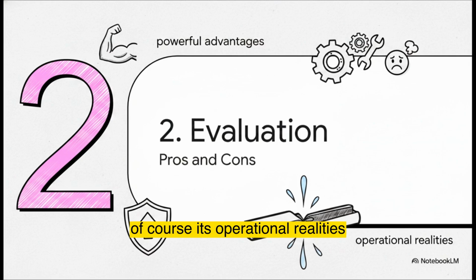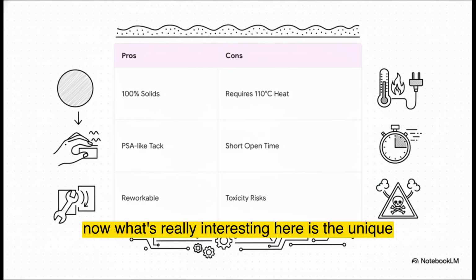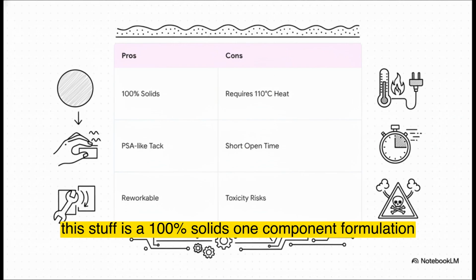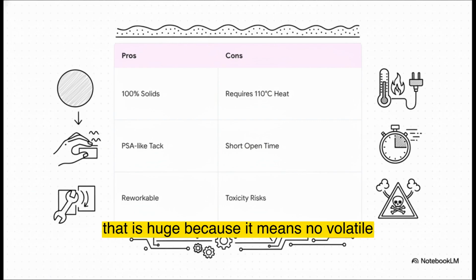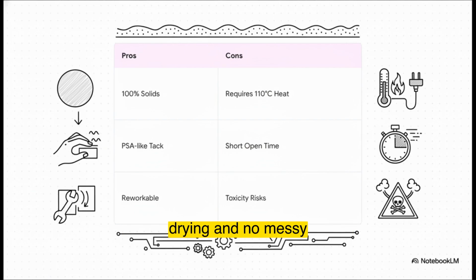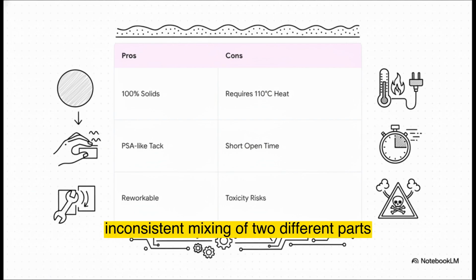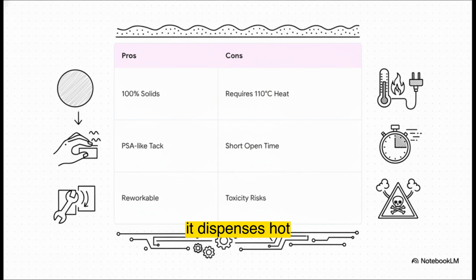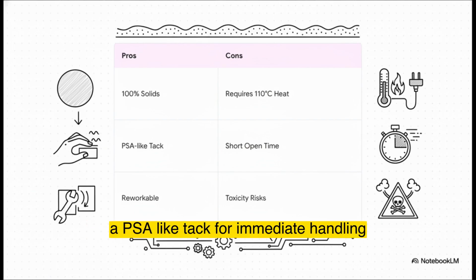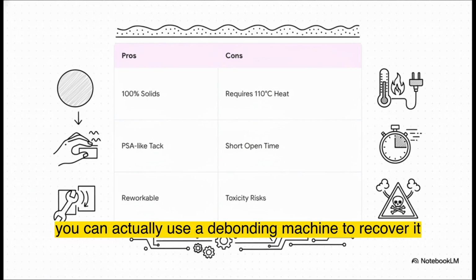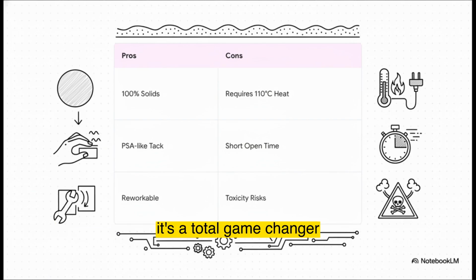Now, what's really interesting here is the unique balance of properties. On the advantage side, this stuff is a 100% solids one-component formulation. That is huge because it means no volatile organic compounds to worry about drying and no messy, inconsistent mixing of two different parts. It dispenses hot, but it gives you a pressure-sensitive adhesive, a PSA-like tack for immediate handling. And, crucially, it is reworkable after curing. Meaning, if you mess up an expensive touch display module on the line, you can actually use a debonding machine to recover it. It's a total game changer.